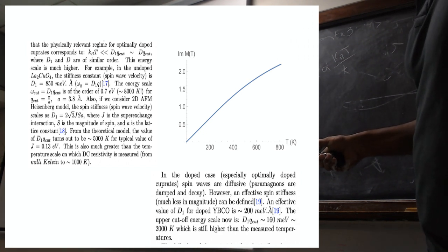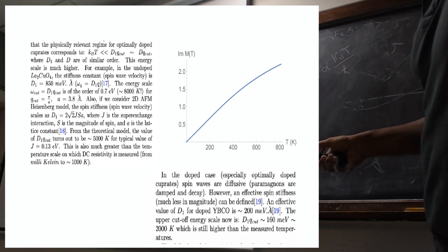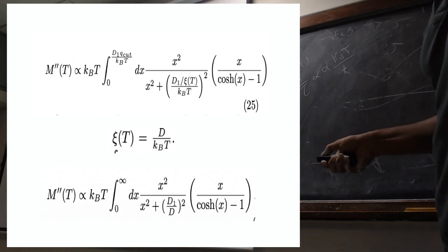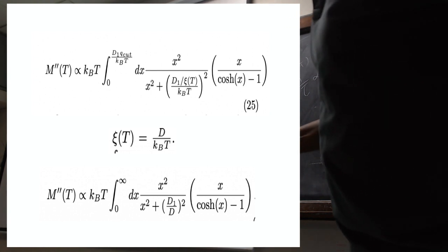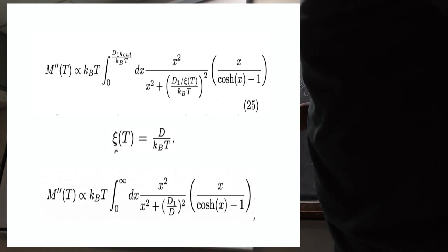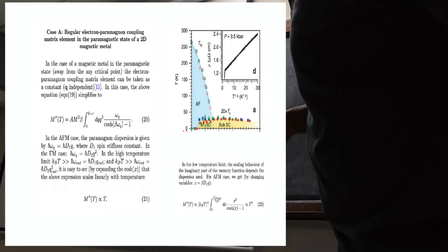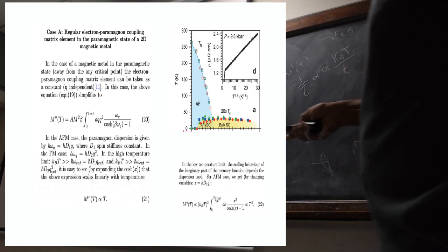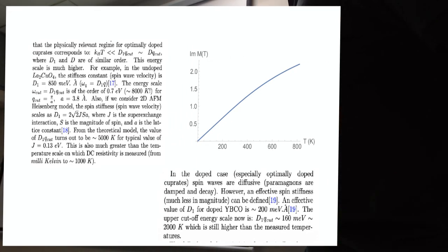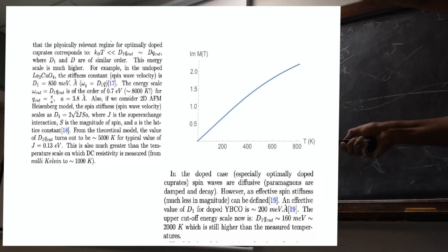So then I looked into the literature for LSCO at undoped d1. The d1 is the value of the spin dispersion. Where did I write this dispersion? Yeah, h bar omega q is d1; d2 is for ferromagnet, leave the ferromagnet, d1 is for antiferromagnet. So I took this d1 value, and also I saw a theoretical model, the 2D antiferromagnet Heisenberg model. By putting in the legitimate value of J and all those things, this value of the upper cutoff comes out to be really large, 5000 Kelvin. The Debye scale here is 5000 Kelvin. You are measuring resistivity up to 800 Kelvin. Okay, so it is actually linear, but then it was saturating.